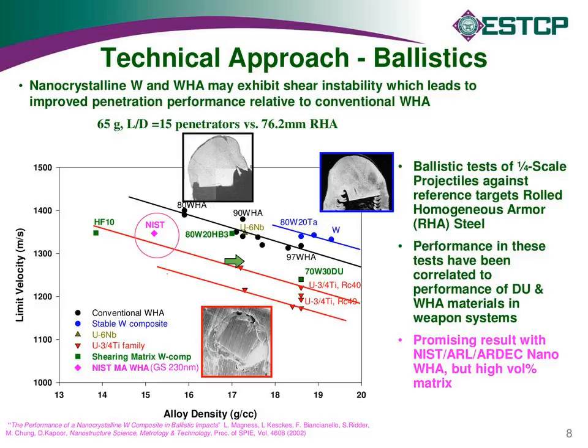Among the DU alloys, for the same density as the 97 tungsten, this is exactly a reflection of what you saw in those two penetration curves. Again, the limit velocity will drop 100 meters per second for the standard U3/4 Ti alloy. And if you go to even higher hardness DU alloys, they develop that adiabatic shear failure even earlier, so less deformation, less mushrooming is required to discard that material, and that actually lowers the limit velocity another 50 meters per second or so. And we have a family of other different DU alloys down here on this plot. So the red lines are the shearing materials like DU.